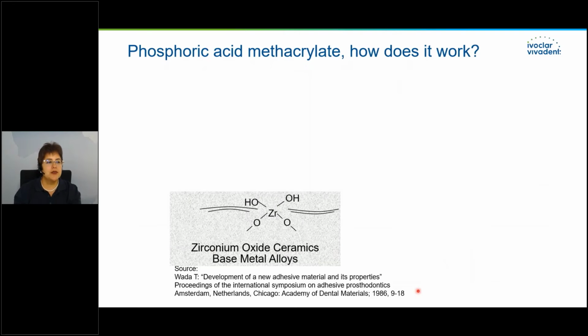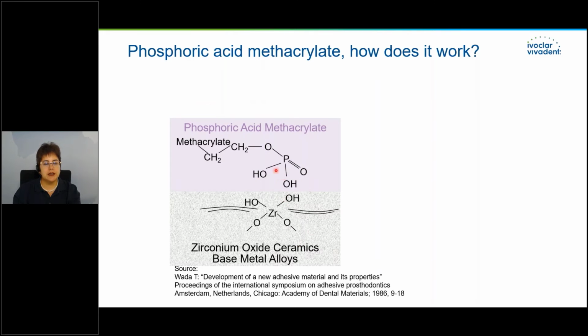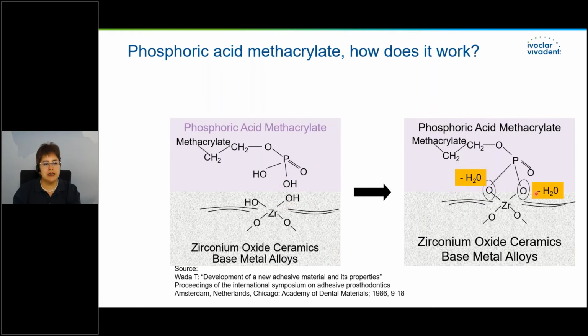Here first you see that on the surface of oxide zirconia, we have these free radicals, these OH. And with the phosphate methacrylate, there will be a reaction like this. We will create bonding and liberate water, and therefore we have a good chemical bond strength with this primer.